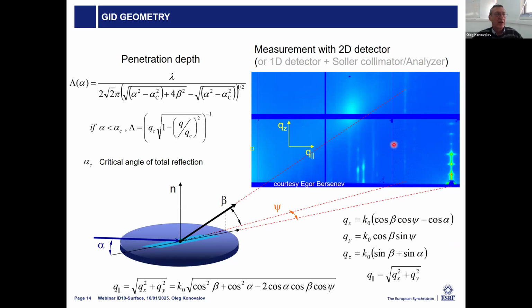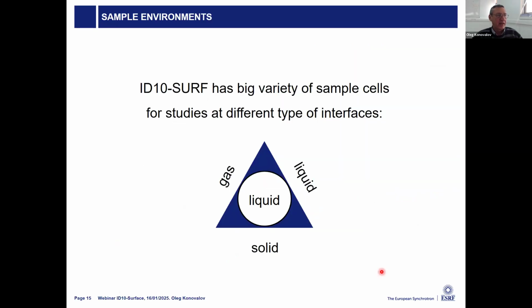So this one picture is measured with a two-dimensional detector, but if we want better angular resolution, we can also measure this with a 1D detector and a Soller collimator or analyzer. Afterwards we can see all these Bragg rods, resolve them, and then reconstruct the structure of our system. Then some words about the sample environments, which is very important for any type of experiment.